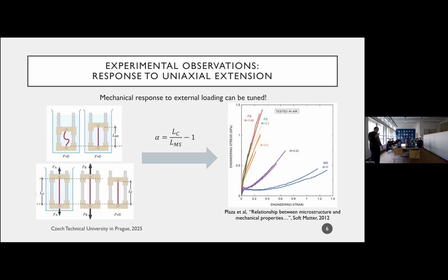What this paper suggested is, let's take a silk fiber, just naturally spun or forcibly silk. We'll put it in water. We'll let it supercontract, so it shortens by as much as it wants. And then we're going to let it dehydrate, but we dehydrate under tension, so we stretch it a little bit. Now, as you can imagine, by doing this I'm changing the microstructure. There are some effects that I'm doing to the microstructure, which I'll show you in a little bit. But essentially, that's what I'm doing.